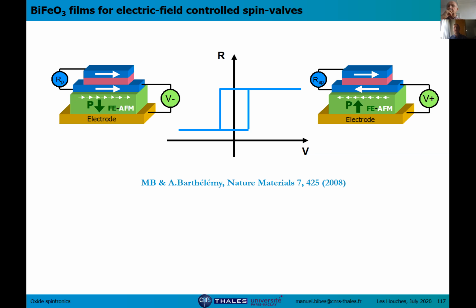So we have some results on BFO junctions where we have manganite as our bottom electrode, which has a low TC, so at room temperature it is not magnetic. And we tried different top electrode materials like tungsten, I think, and maybe iridium, that are not magnetic. And we see also tunnel electroresistance. Then what determines the amplitude of the tunnel electroresistance is a number of parameters of the metal, for instance its work function. If you have a larger work function, typically we get larger tunnel electroresistance, but the devices can sometimes be harder to switch.